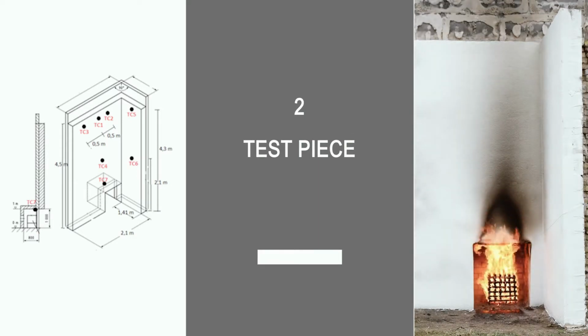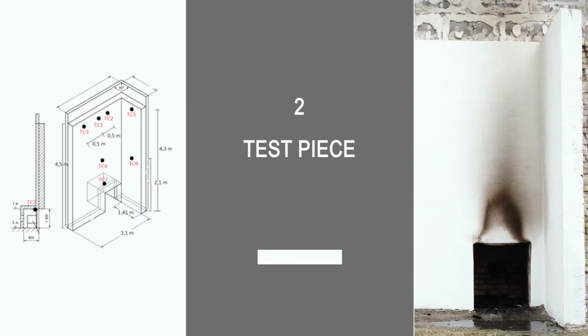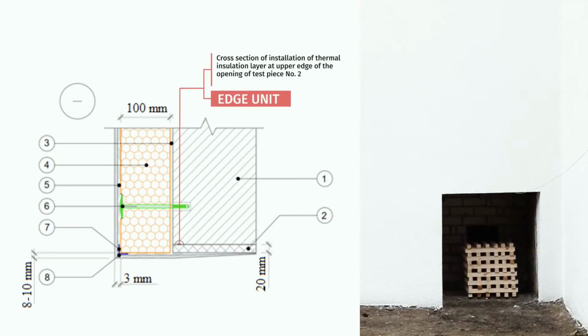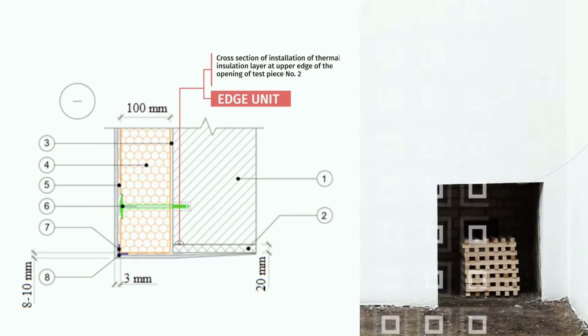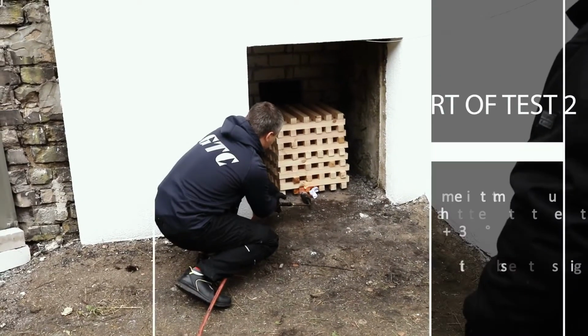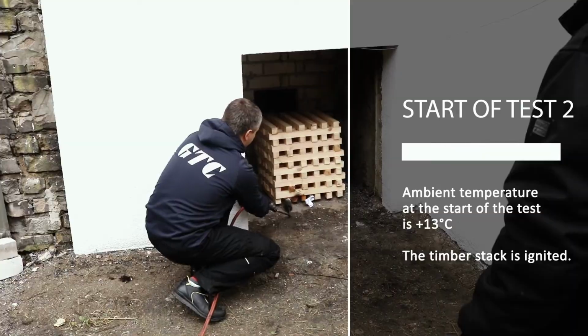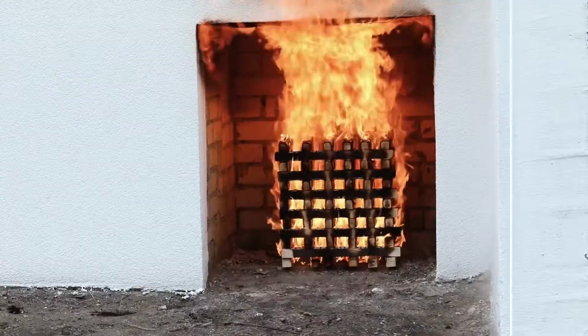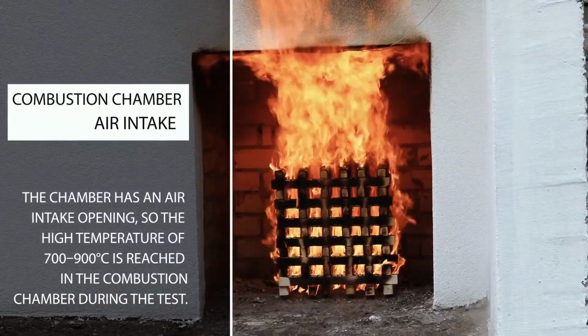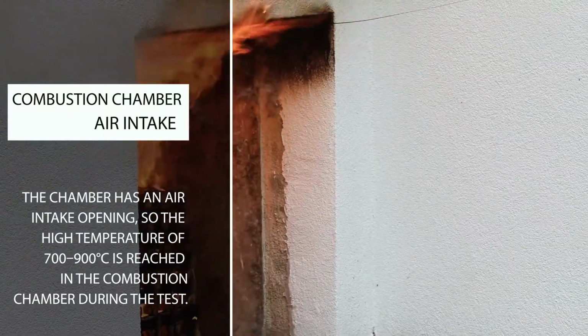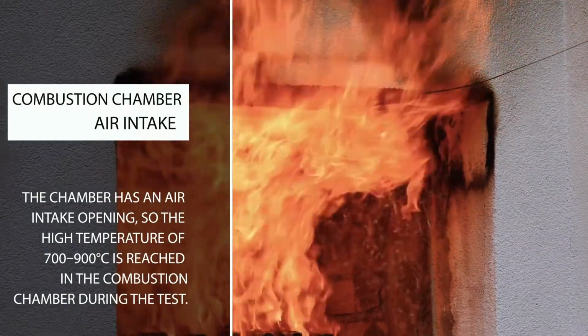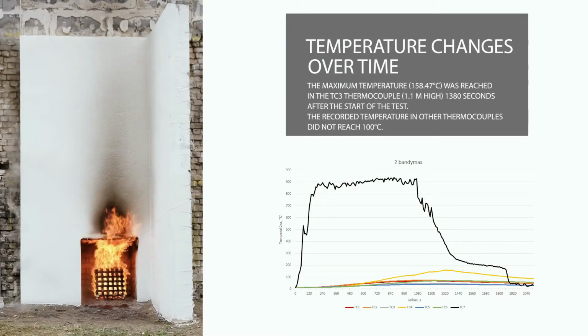Second test piece. Cross-section of installation of thermal insulation layer at upper edge of the opening of test structure number 2. At the beginning of the test, the timber stack is ignited. Ambient temperature is plus 13 degrees Celsius. The combustion chamber has an air intake, so the temperature in the combustion chamber reaches some 700 to 900 degrees during the test. The diagram shows that the highest temperature above 158 degrees Celsius is reached in thermocouple TC3.